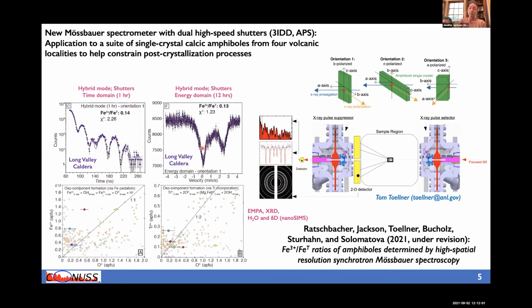And this is really made possible using a new spectrometer for Mössbauer spectroscopy that has been designed and developed by Tom Toellner. The spectrometer sits at 3-ID-D at the APS, and it takes advantage of the hybrid mode beam time. There's a pulse selector and a pulse suppressor. And so this allows Mössbauer measurements using essentially the full beam and data collection times that are reduced significantly